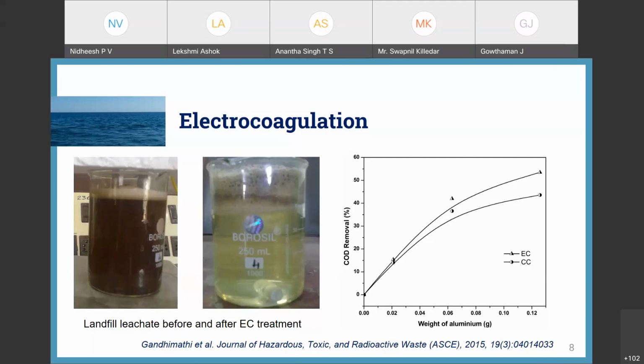But electrocoagulation itself gave good results compared to the rest. Here we used aluminum as the anode. We also tried chemical coagulation, that is CC, and then compared the efficiency. The chemical coagulation also depends on the weight of aluminum. From Faraday's law, we find out the aluminum coming out from the system, and we also check the weight loss of the anode before and after the treatment.